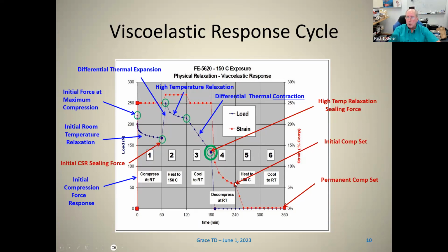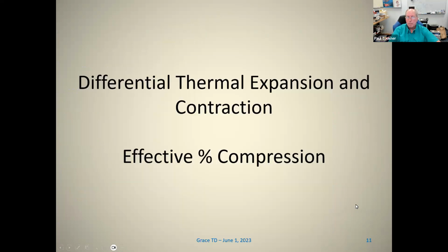Then if you take the material and heat it back to elevated temperature for a short period of time, say 30 minutes or 60 minutes, and then take it out and cool it back to room temperature, what you should have is that it recovers to its original shape and thickness, assuming there's no degradation of the material. So this is a characteristic response that shows how you can compare continuous testing to discrete testing and how they compare in an actual application.